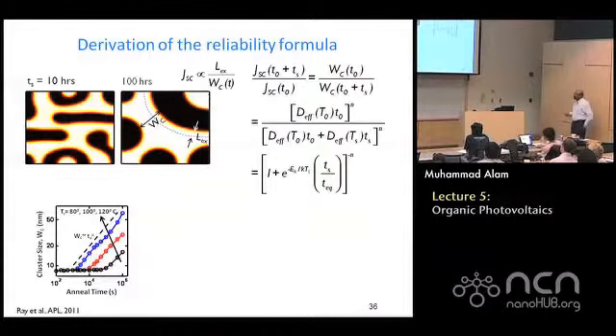So what you can do is look at what W, the width of this region, was when you shipped the product to the consumer, and how W evolved as a function of time. You put in the short circuit current, L exciton, which scales with D to the power N. But now remember, this is the operating temperature, hence the T naught, and this is the effect of the initial anneal, how long you annealed it when you shipped the product.